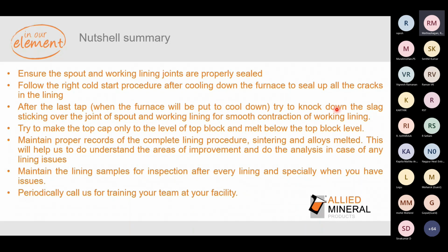Try to make the top cap only to the level of the top block and melt below the top block level. Because if you make any kind of heap, this is not going to sustain for a long period of time. If you make a heap with sodium silicate, it cracks easily, and this can even lead to unsafe operations. Since the sodium silicate does not have the strength, it always stays there as a cracked one. It also gets into your liquid metal while tilting the furnace, and it can create inclusions in your castings. To avoid this, try to choose a proper top cap refractory and maintain it to the top block level.